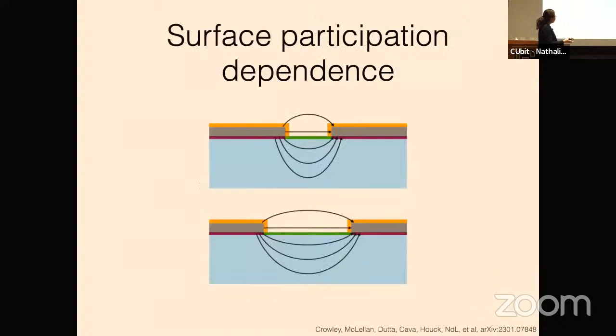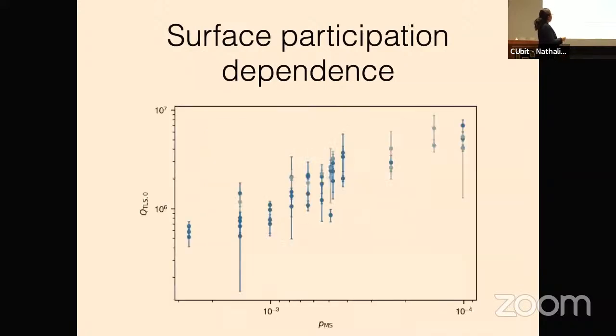Okay, so the next thing that we can do is make many different devices that are different sizes. And the general idea is that I pull my capacitors apart, and then that blows up the mode, and the fraction of the field that overlaps with a little layer of surface goes down, right? So I just changed the surface participation. And what we see is that as you change, so I know this is very confusing, but the devices are getting bigger as you go to the right, so the surface participation is getting lower. That's why it's in this weird inverted axis.